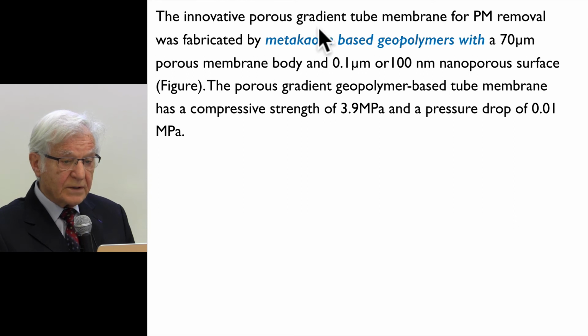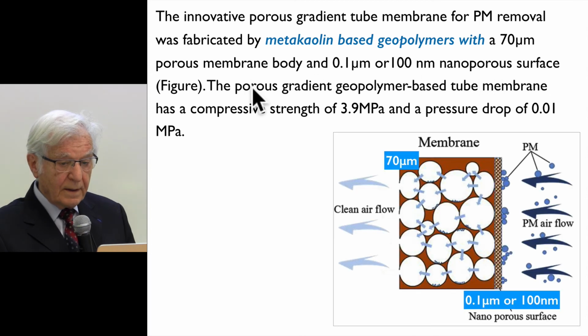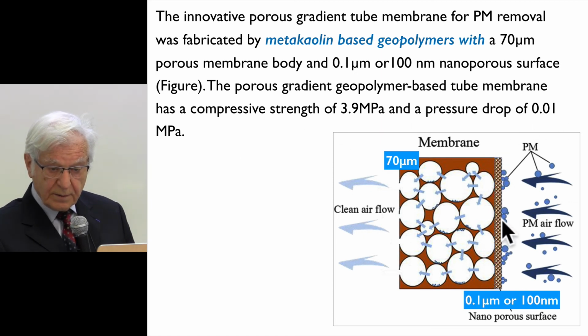The innovative porous gradient tube membrane for PM removal was fabricated from metakaolin-based geopolymer with a 70 micron porous membrane body and a 0.1 micrometer, or 100 nanometer, porous surface. The porous gradient geopolymer-based tube membrane has a compressive strength of 3.9 MPa and a low pressure drop, so it works. So this is the membrane here, 0.1 micrometers, 100 nano, the particles here, and they go